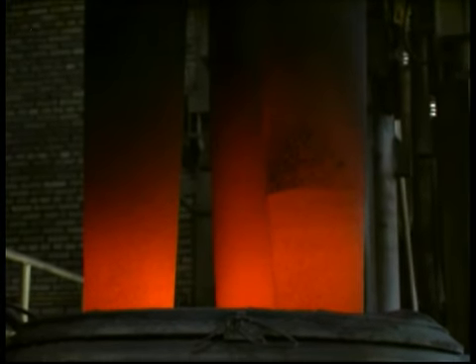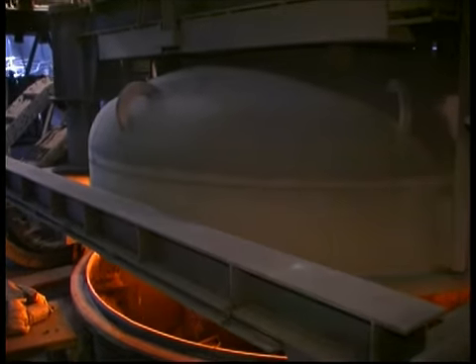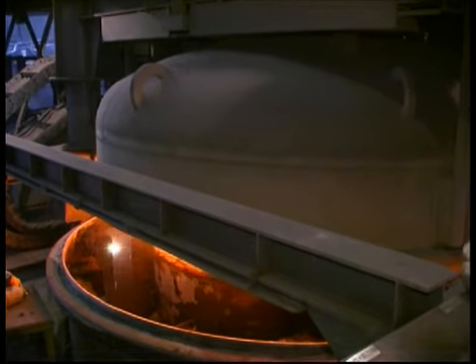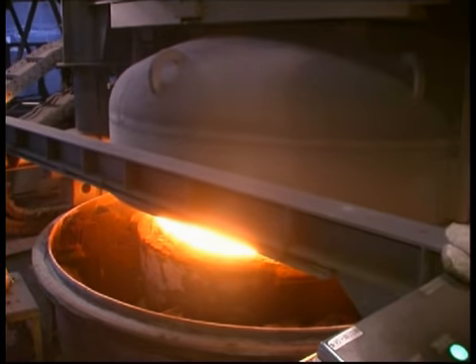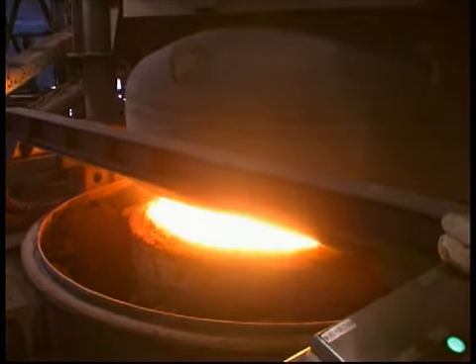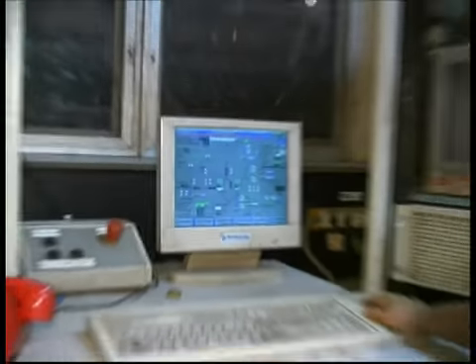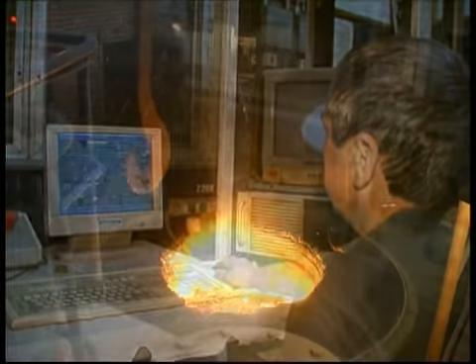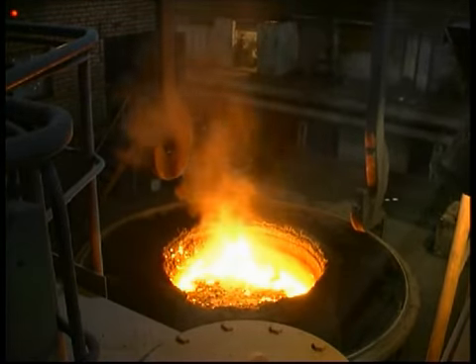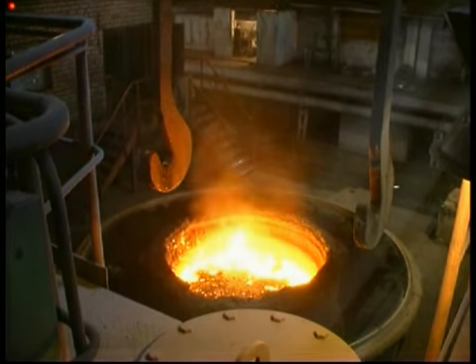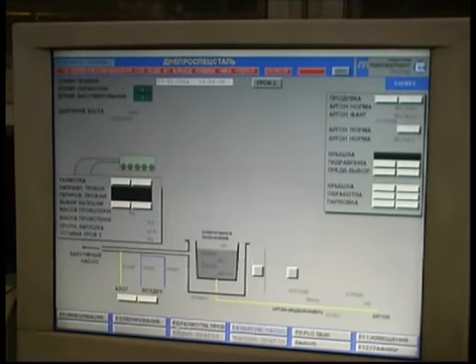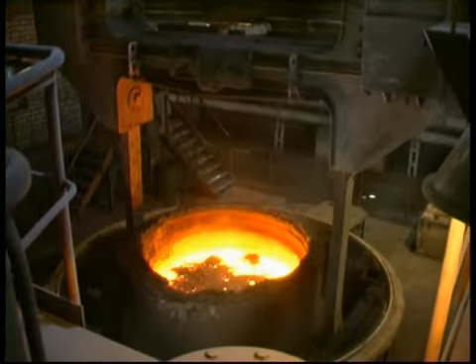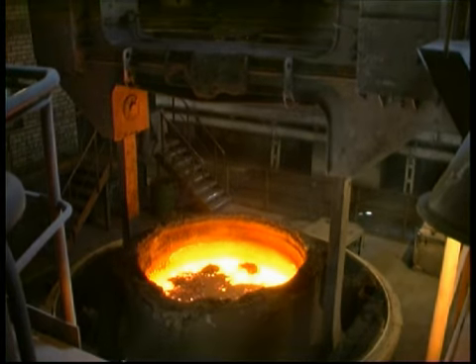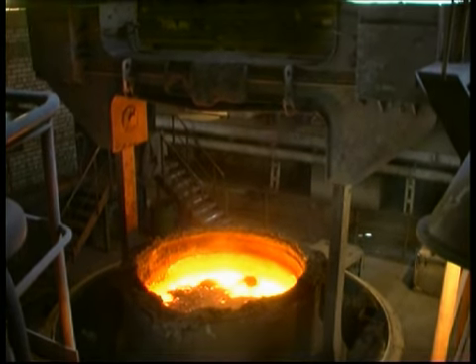Additional metal refining from non-metallic and gas inclusions, important for high-grade steels, can be achieved using equipment and technology of Mannesmann Demag company. A vacuum degassing unit was installed by German specialists in 1999. For example, for bearing steel, it provides a residual content of oxygen and hydrogen of 0.001% and 0.0002% correspondingly, that conforms to the requirements of the most particular customers.